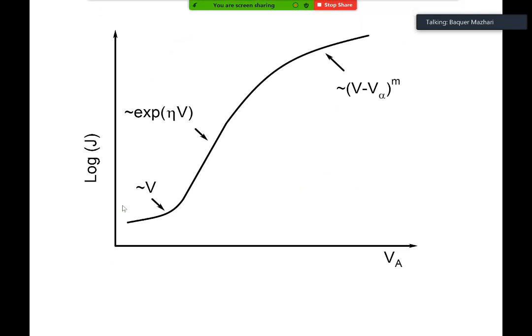It's very common, when one measures these rectifying devices, to get a characteristic like this. At low voltages, we get a shunt resistance, a linear behavior. Then we have an exponential characteristic, and then it goes towards a power law kind of characteristic. And often, for a quick estimation of built-in voltage, people tend to fit a straight line here, fit a straight line here, and at the intersection of it, calculate a threshold voltage or a sort of built-in voltage for the device.